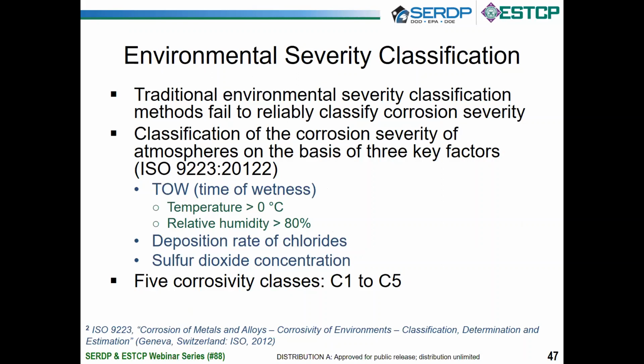What's currently used to assess environmental corrosion severity is ISO 9223. This classification looks at 3 key factors, which are time of wetness, deposition rate of chlorides, and SO2 concentration. The main issue with this method of classification is that a wet environment is defined only as greater than 80% relative humidity and greater than 0 degrees Celsius in temperature.